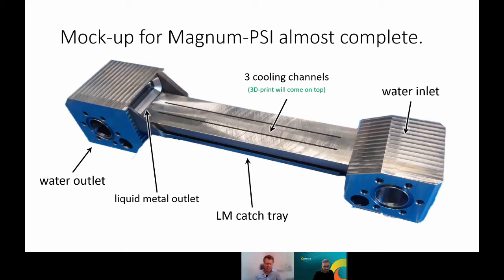Right. So in a standard diverter or a standard wall per se, you have a constant neutron flux. The neutron flux damages the tungsten, which creates voids, vacancy clusters, and so forth. Now, when you slab liquid metal on top of that, conceivably, those voids or vacancy clusters could fill up with the liquid metal, which could do potentially one of two things: it could influence the flow mechanics, or it could impact surface chemistry. I do not know offhand what I would expect, whether that would be an issue, but I do wonder whether there is any plan to repeat those experiments you did with the damaged tungsten samples. Or damaged tungsten wall, basically.